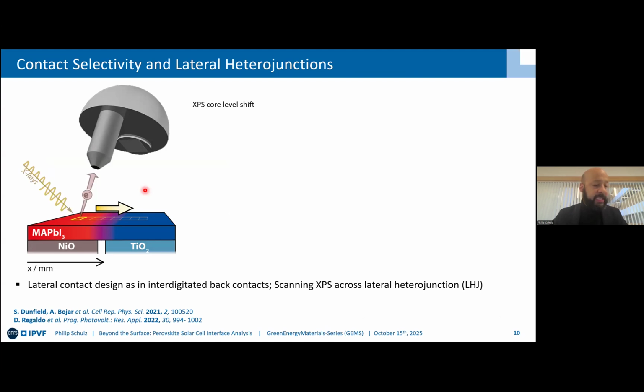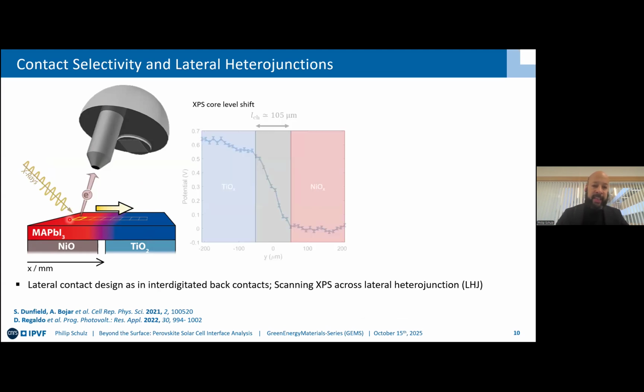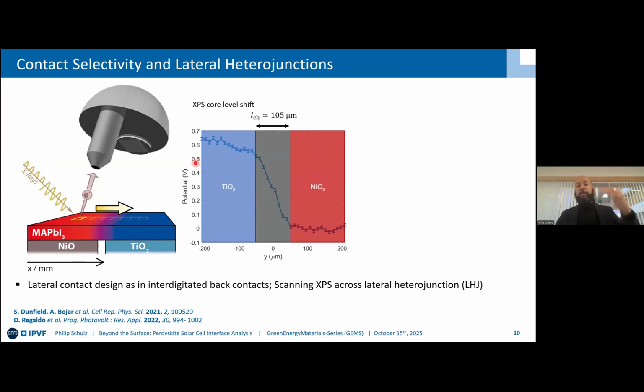Something that we have started in our team with Sean Dunfield and Alexandra Bojar and Davide Regaldo, which is now pursued and further deepened by Pilar Lopez Varo. And we see that starting off at the left-hand side, going to the right-hand side, or vice versa, we track the change of the surface potential across this channel. We make out a region here above the nickel oxide that is set at 0, and then see effectively the built-in field between those two layers. Now, this is a little bit of a playground for us in order to test and to model that.